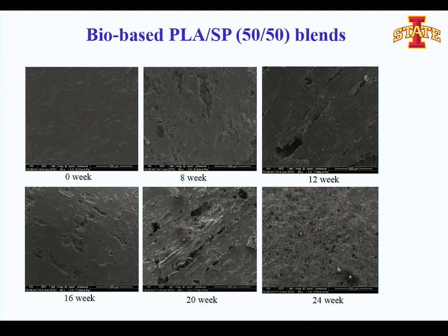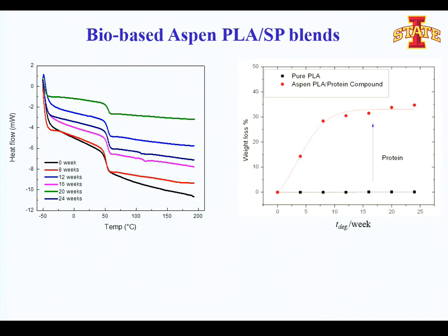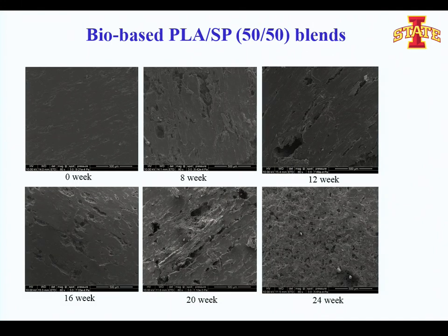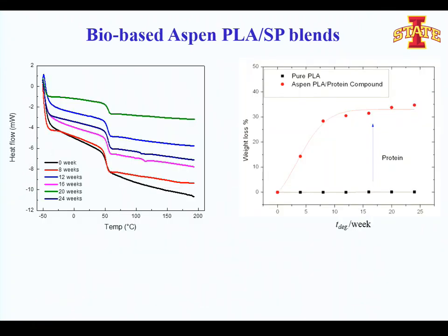Checking the morphology by SEM: with no degradation we have a very smooth surface; with increasing degradation time we have a rough structure with cracks everywhere on the surface; and after 24 weeks we have a very porous material, due to degradation of the soy protein. [Audience question: is that because it's brittle or because it's breaking down?] It is real degradation — the molecular weight decreases and the material becomes very brittle — so it is both.